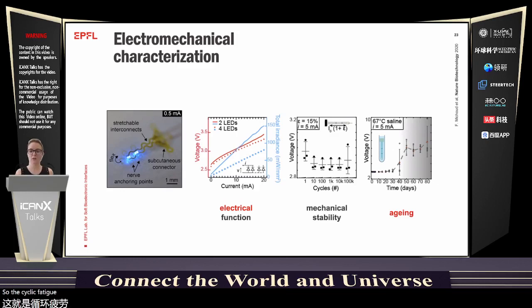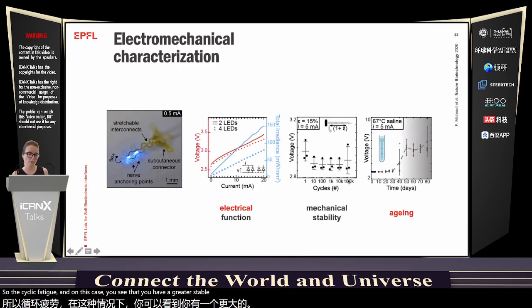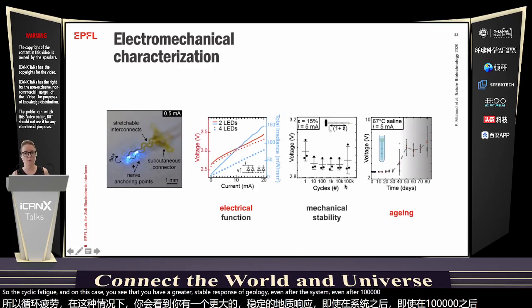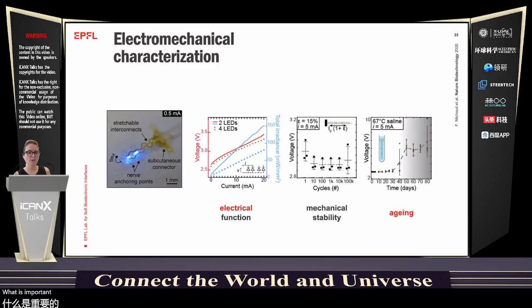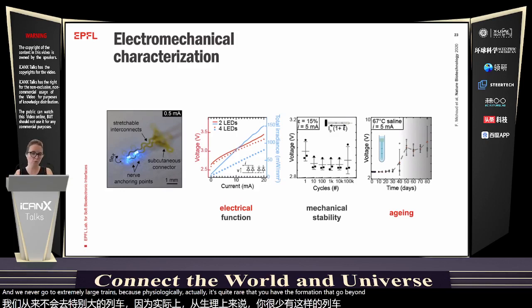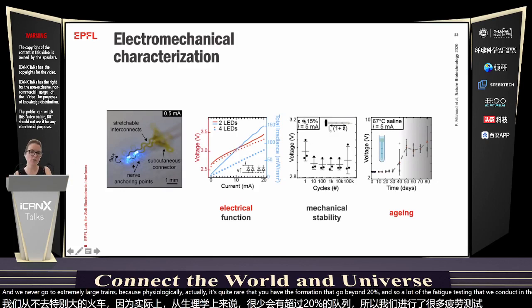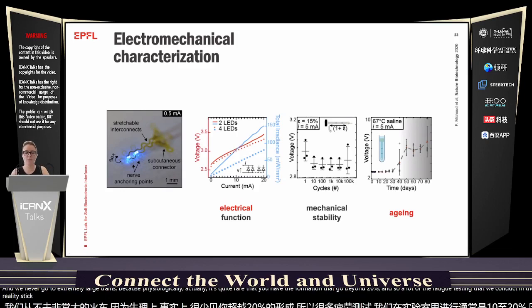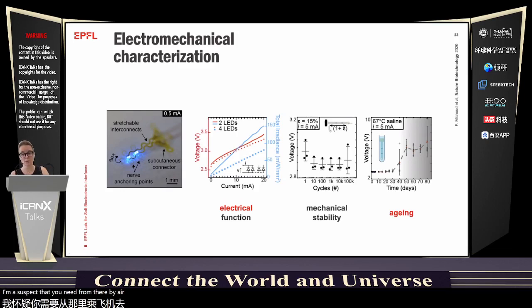And in this case, you see that you have quite a stable response of the LED system, even after 100,000 cycles. What is important is the value that you choose for your strain. We never go to extremely large strains, because physiologically it's quite rare to have deformations that go beyond 20%. So a lot of the fatigue testing that we conduct in the lab is usually between 10 and 20%, because these are the realistic specs that you need from the biological environment.